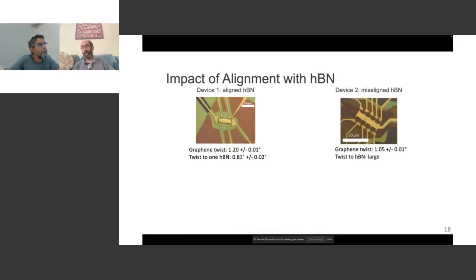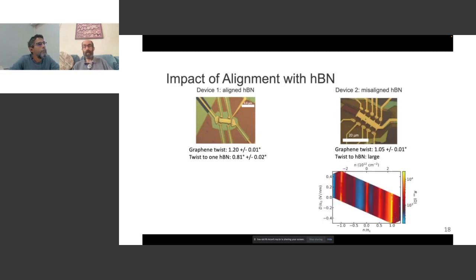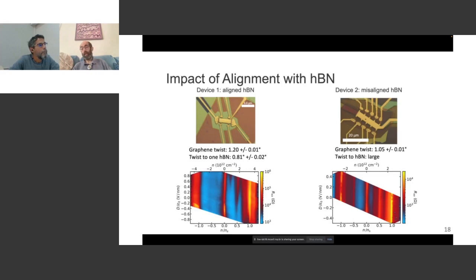Since then, we've measured lots of devices that were not aligned with boron nitride, and that was the case for most of the other samples people had looked at. And on the face of it, the conduction looks rather similar, but if you look at the details, it turns out that there are a number of clues that something is different here. The resistance scale is much higher in the aligned case, and for those of you who are familiar with graphene, you know that at the charge neutrality point, you don't expect a really extremely insulating state, and here you get a much higher resistance than you'd expect normally for graphene.